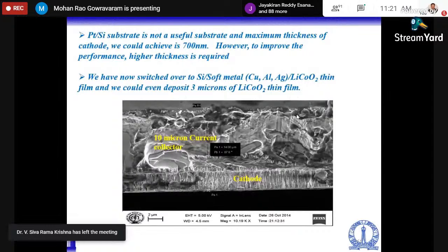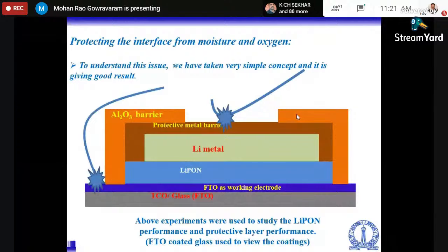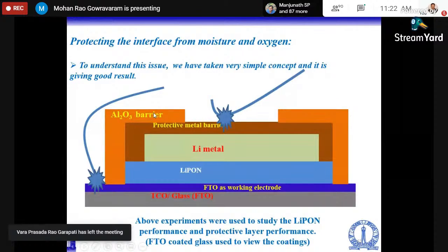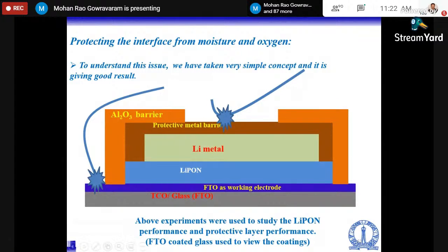Now, then you have to protect the interface from moisture and oxygen. How do you protect the layers? What is done here is that after all the depositions are done, on the top we have done a aluminum oxide barrier layer to protect the entire battery structure from the ambient air. So this aluminum oxide has to be perfectly dense without any pinholes. And then you give a metal layer on the top and then take the connecting out.